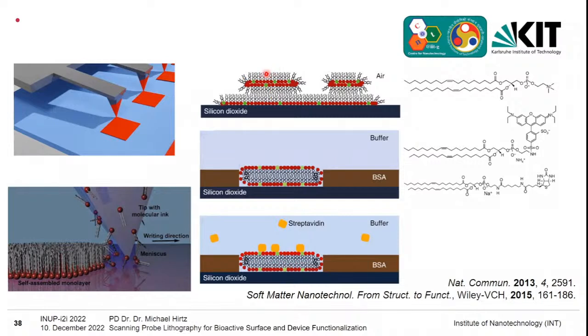So here you have the tails-out configuration, and the hydrophobic chains are going outside to the air. If you have a hydrophilic substrate, the head groups will go here like this. But as soon as we put them into a buffer solution, like transfer it to a liquid environment, then they rearrange, and we will end up with supported lipid bilayers in this case that have the biological tails out version. And then, and this is an important step, we can use the functional lipids, for example, here the